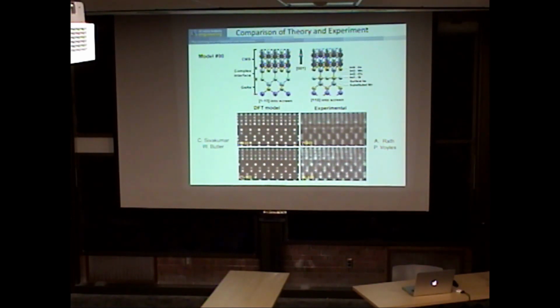So what happens? The theorists immediately start off and say, we'll calculate the minimum energy, right? The interface of the minimum energy. And of course they start doing this, and you start different positions for all the atoms, you try and get them to minimum energy. And you find out there's no global minimum, right? There's no real strong minimum. So then they change concepts of how you do it. Now what you do is you talk to the TEM person, did some yields and did other things, and you start trying to fit a model of an interface with atoms mixing up a little bit to try and simulate the TEM image that you see.